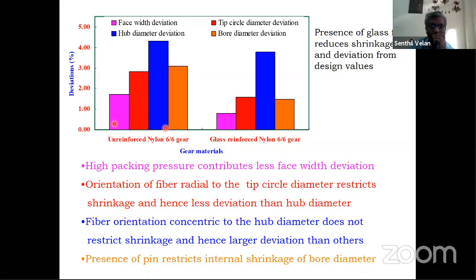In this slide, the packing pressure contributes to less face width shrinkage. Why is the face width deviation very small? Because the packing pressure contributes more in that particular direction, you are packing normal to it, whereas you don't pack along the tip circle. The packing is normal to the face width, which means the three parts or plates are holding each other. The orientation radial to the tip circle restricts the shrinkage and hence gives less deviation. Orientation concentric to the hub diameter does not restrict shrinkage and hence gives large deviation, and the pin restricts the internal shrinkage and so on. So even at different locations, you end up with different dimensional shrinkage.